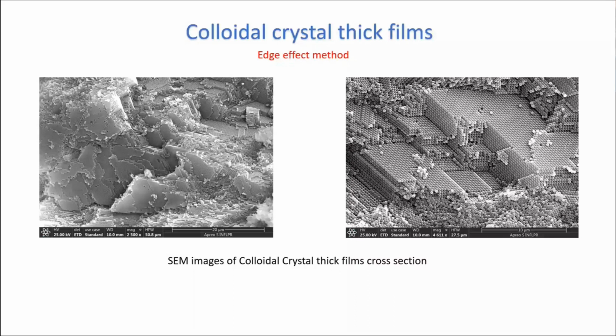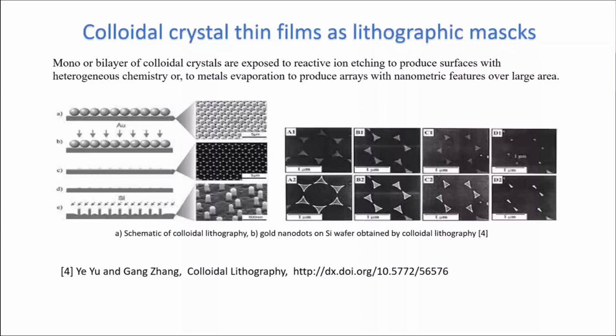A single layer or bilayer of this colloidal crystal can be used as a lithographic mask in what is called colloidal lithography, an analog of classical lithography, but instead of the lithographic mask, we form a single or double layer of this kind of sphere. Vapors of metal are infiltrated through the pores of the film and condense on the substrate, the spheres are dissolved, and we obtain an array of metals with nanometric size.